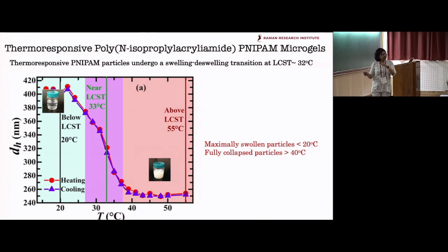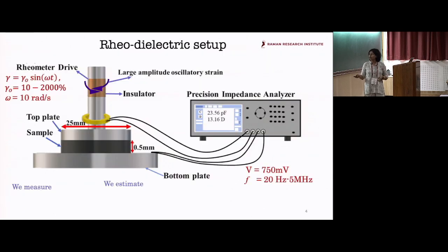It's transparent here because the particles have swollen up because they've incorporated water. So there's no refractive index mismatch, no scattering, therefore it looks totally transparent. But here, at high temperatures where it's totally collapsed, these are like tight globules of polymers, no water, so there's a refractive index mismatch, so you can see how opaque it gets here.